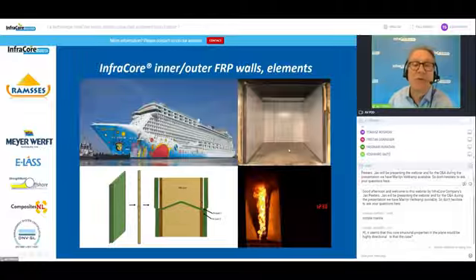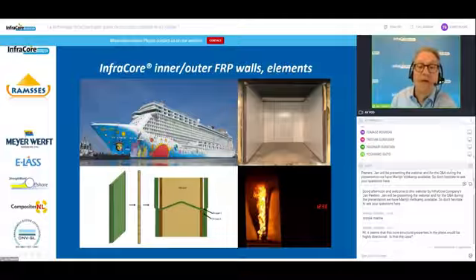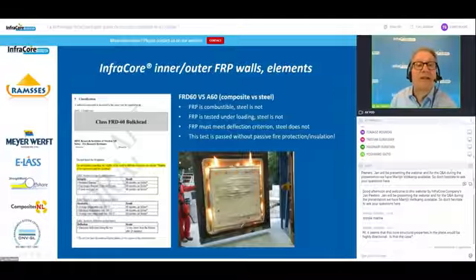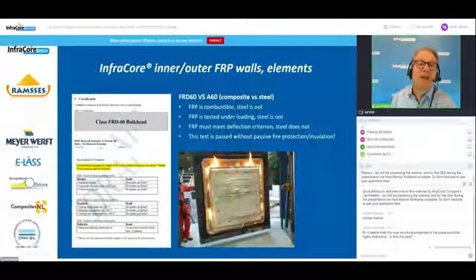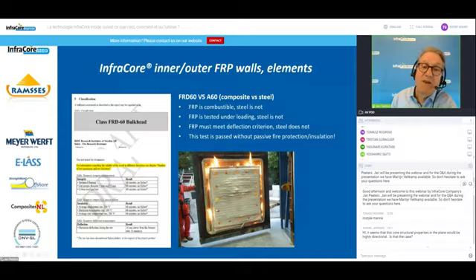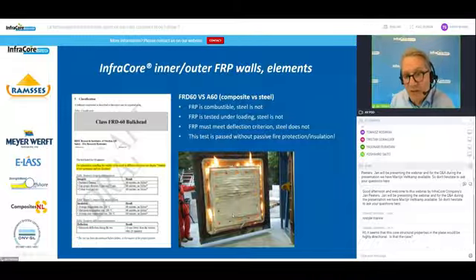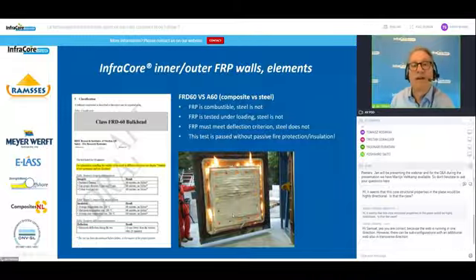These are the panels which would define a cabin. And we've done the fire testing, and we now have an FRD 60 bulkhead fire classification on InfraCore. But what is interesting, when you expose InfraCore to fire, you can burn away the resin, but because the fabrics are still nicely woven through the core, you do not lose your fabrics. The fabrics will stay in place, so you will always retain some residual strength even after exposure to fire.